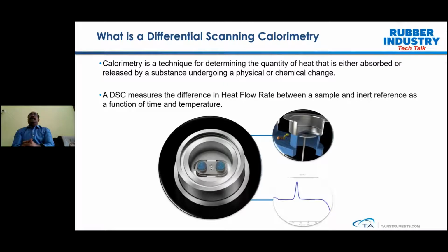Let's talk quickly about the DSC part. So what would DSC be doing? DSC is basically a differential scanning calorimeter. It will measure how much heat is changing with respect to the temperature of your sample. So we put the sample and reference, and then we subject them to heating, and then we can see how the sample is undergoing changes, especially when it undergoes any phase transition. It could be glass transition temperature, crystallization, and melting. So then we can measure the associated heat flow of that.